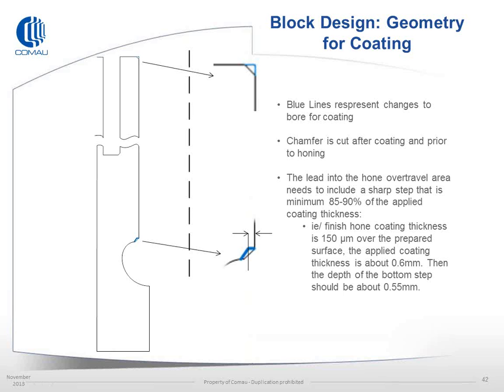Some of the changes that would be integrated into the block design, typically the chamfer at the top is placed in prior to honing. This would be recommended to be done after coating process because we would like to have a square entry for the surface prep as well as the coating process and have that cleaned off. Again, this is only if we're talking a full bore coating prep. Similarly, at the bottom of the bore, typical applications have a blended chamfer into the bore. It's recommended to put in a step that's at least 85 to 90% of your target coating application. This will allow for a significant break point at the bottom of the bore to minimize any chipping or breakage into the bore area from the coating to the non-prepped surface.